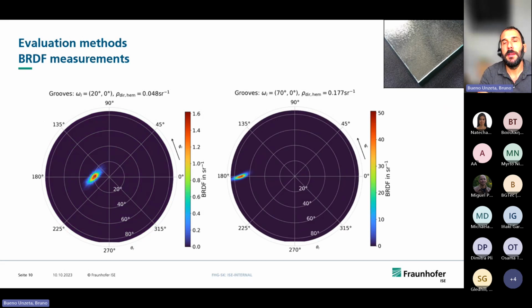So if we take now the slightly structured glazing I mentioned before, these grooves, then the BRDF looks a little bit different. For 20 degrees incident angle, we have at 20 degrees a peak. This is scattered. It's not as small as before, but we reach values of 1.6. This is already above the threshold. The problem is more prominent for higher incident angles. Here for 70 degrees, we reach values of 50 inverse steradians, and this is way above the threshold I mentioned before.